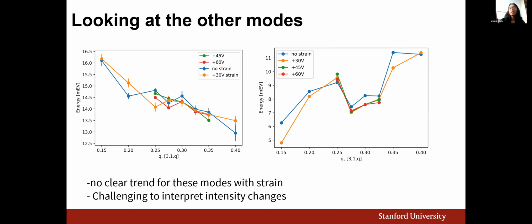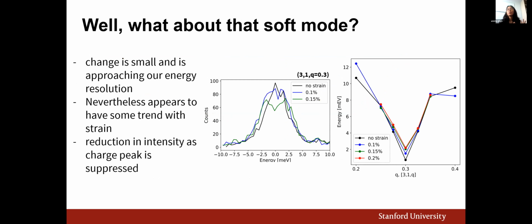Okay, so finally, we can take a look at what's happening to that soft mode. So here I'm plotting a series of scans that were taken at the CDW wave vector for different values of applied strain. And we can see that there is some intensity that is moving to higher energies. And we also see that as we apply more strain, the intensity that we're seeing is going down, and that's primarily because the diffraction peak associated with the CDW wave vector is actually being rotated, right? So we're losing intensity at our elastic line.